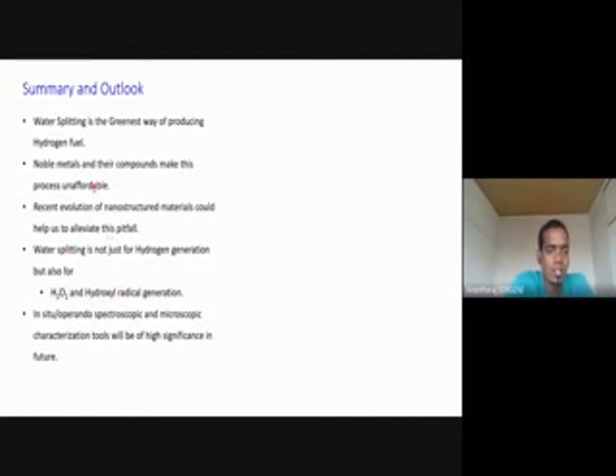And one more thing is that people still don't know what makes a catalyst highly selective for four-proton oxidation or two-electron two-proton oxidation, which I believe in situ or operando spectroscopic and microscopic characterization tools will be highly significant in revealing, such myth behind the selectivity difference between a few metals. So if you want a good OER electrocatalyst, stick with the metals I have shown earlier. If you want good selectivity for hydrogen peroxide evolution via water oxidation, stick with the metals which do not show OER activity. These are the things that you should take away from this, I guess.